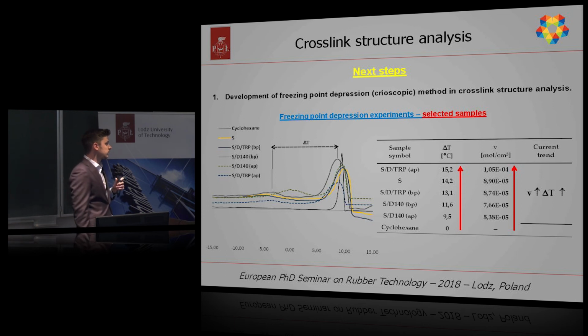So, coming to the end, what about next steps? Firstly, I'd like to develop the freezing point depression method, or otherwise the cryoscopic method, in crosslink structural analysis, because I performed some initial experiments on selected samples, and I noticed some positive trend, because when crosslink density calculated from the Flory-Rehner equation increases, then the delta T also increases, and the delta T is the difference between the cyclohexane crystallization temperature, which was introduced to the DSC crucible during analysis, and the cyclohexane crystallization temperature, which was trapped between the crosslinks in the rubber structure.